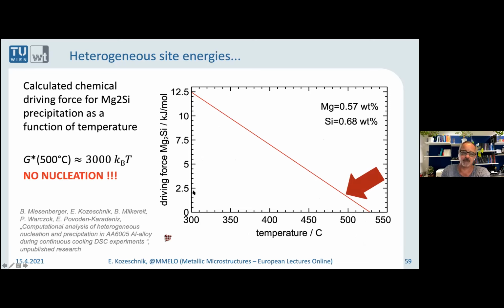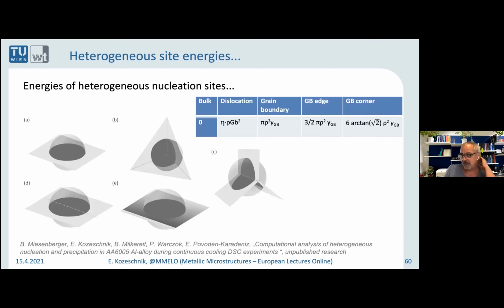It's roughly 2 kilojoules per mole. That will give a nucleation barrier of roughly 3000 kBT. And for 3000 kBT, remember that you have to put the value of 3000 in the exponent with a minus, so e to the power of minus 3000. Your pocket calculator will have an underflow, so it's practically 0. So there will be no nucleation if you simply use all the ingredients that I was proposing so far.